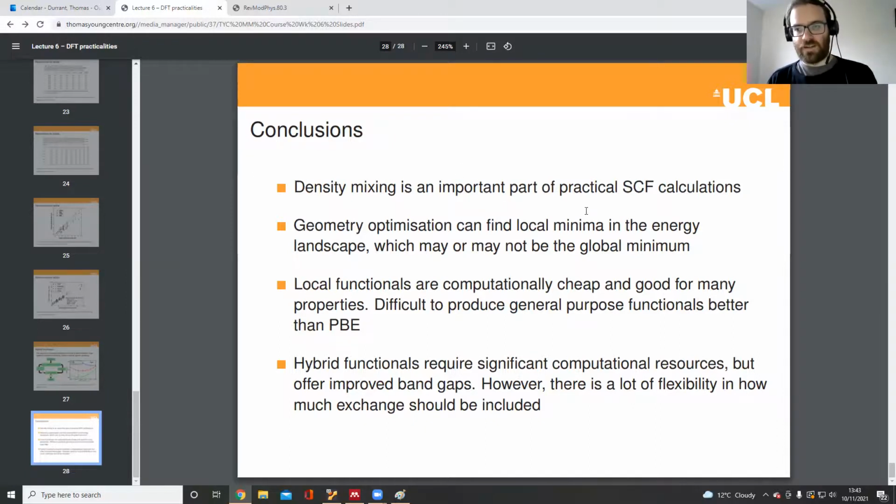If that's not the problem, there are a couple of things you can fiddle with to try and improve the optimization. And this second point that I made, that I think is very important, is that when we do geometry optimization, we're going to find a nearby low energy structure, not the lowest energy structure that's possible. That's something that we always need to bear in mind. You can't expect DFT optimizers to take the atoms you put in the input and then find the lowest energy structure for them. They're just going to find their way to the nearest local minimum.